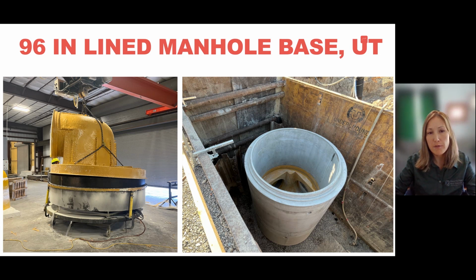And we see that very often. But one thing you have to remember is that microbial induced corrosion happens in the air, not in the trough zone for the most part where you have the flow, but because of the suspended particles from the wastewater. So most likely you're going to have deteriorating walls rather than a deteriorating channel.